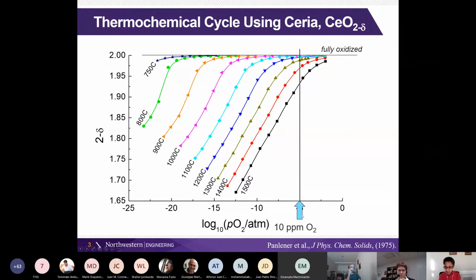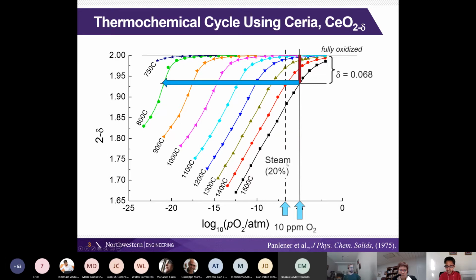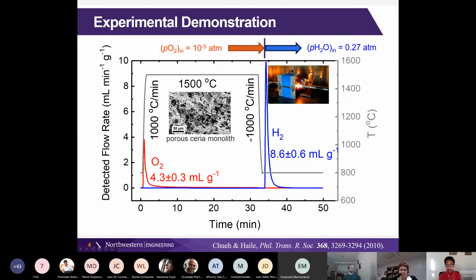We do a sweep of the material at high temperature. So we have an inert gas that has a low oxygen content in it. We heat it up to 1500 C. That induces a loss in oxygen by this amount here. We then quench it to 800 degrees Celsius, introduce steam at that temperature. Say 20% steam would give you an effective oxygen partial pressure of around 10 to the -7 atmosphere by the thermolysis reaction. And then the material in response to this oxidation condition returns back to the condition of delta being equal to 0, where delta is this non-stoichiometry. So we calculate that out, and that turns out to be 8.6 milliliters of hydrogen per gram of oxide per complete cycle.